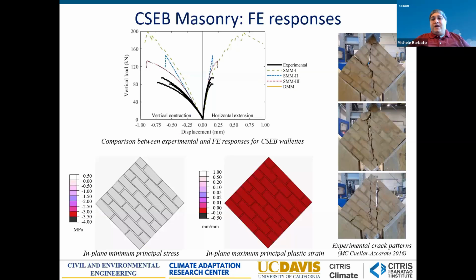And the reason is for earthen construction, the mortar and the blocks have a very similar strength, which is very different from what you have in ordinary masonry, where the mortar is typically weaker. So the basic assumption of the simplified micromodeling approach is not satisfied. And this is shown here on the right by experimental results, where you can see that the cracking of the structure is not limited to the mortar. It generally goes through the blocks and the mortar, almost as if the material was a homogeneous material. So what we found is when we were using the simplified micromodeling approach, we were overestimating, even by a factor higher than 2, the actual strength obtained from experimental testing. You can see here the black lines corresponding to the triplet that is shown here.